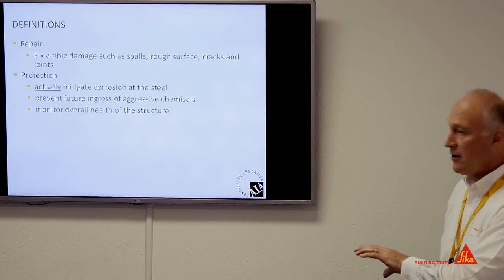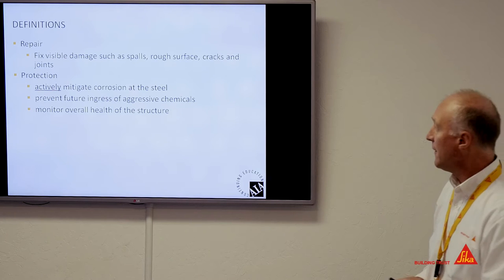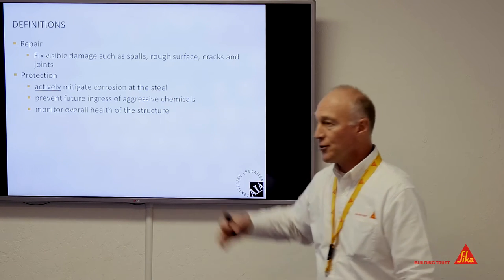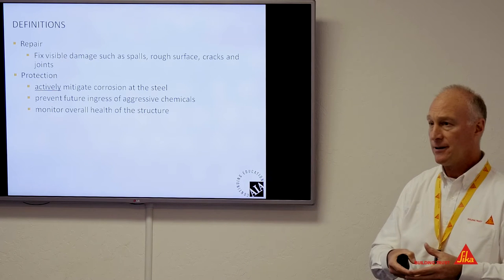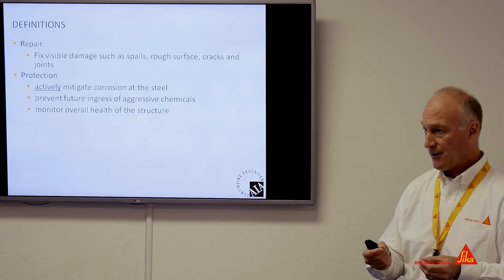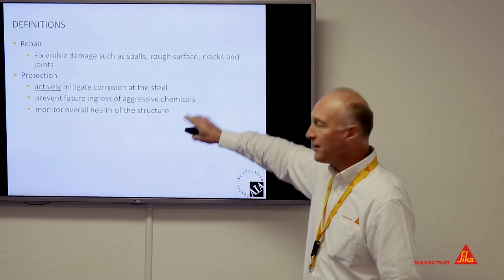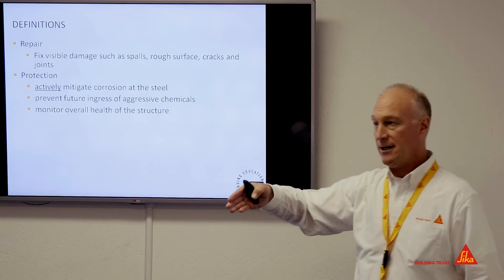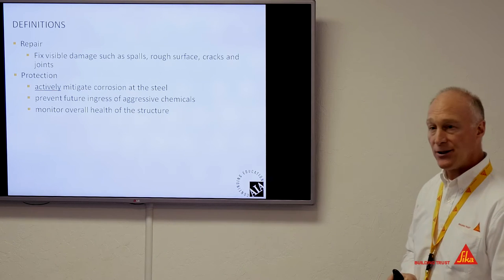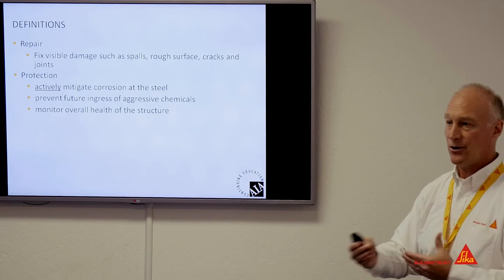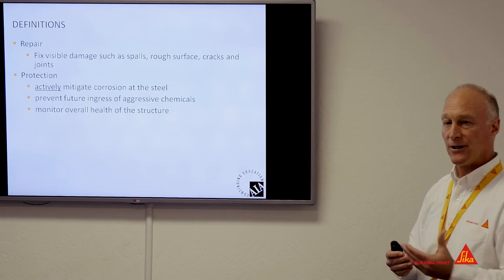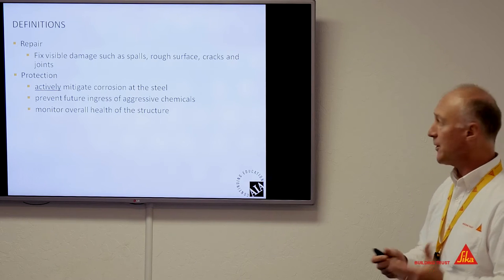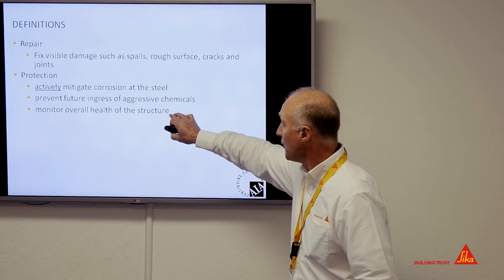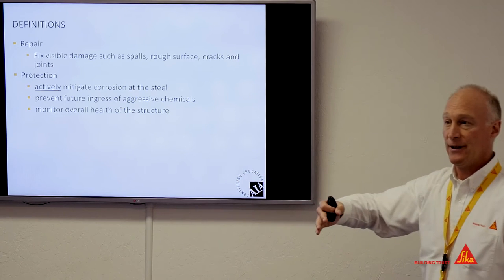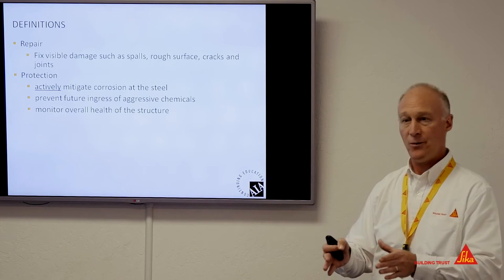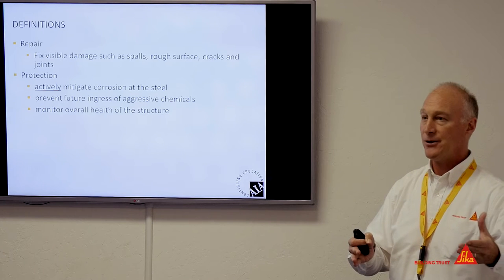Protection, though, I break into a three-pronged approach. There's active mitigation, where we're trying to do something on the surface of the steel to actively mitigate that corrosion process. Then there's the application of a coating on the surface of the concrete. That's maybe more passive, but we're trying to prevent ingress of oxygen and moisture into the concrete, so it prevents the steel from existing in an environment that's getting increasingly worse. And then I think it's always a good idea to monitor the health afterwards. Take a look before, do your repair and protection, and then monitor it going forward to see how it's performing over time.